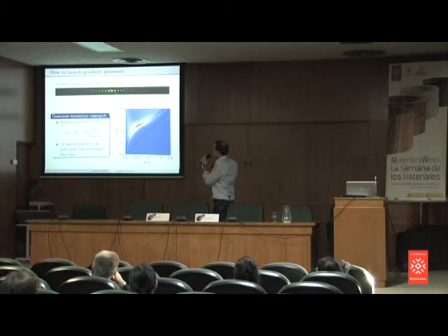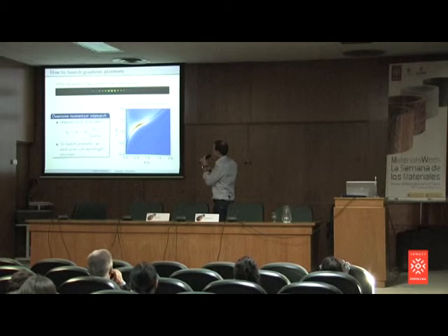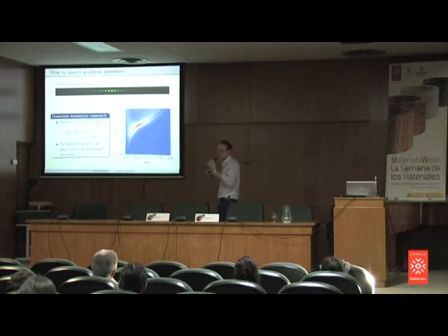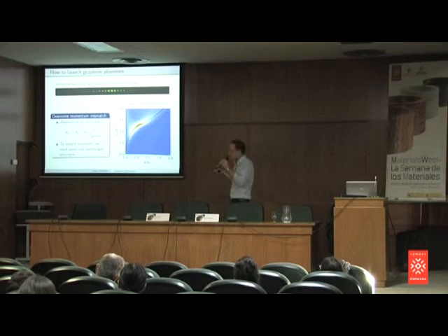And light comes in here, and most of it goes through, of course, in zeroth order, and then you have diffraction order 1, 2, 3, -1. And what happens here is, well, the wave vector of the light picks up some momentum, to the right, which is somehow proportional to this lattice spacing. And this is the mechanism that people use to get photons from the light cone, from here to there, to the plasmon dispersion, and then they can excite plasmons in graphene or in anything else.